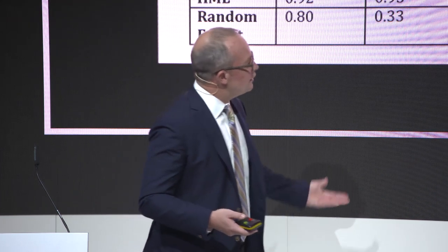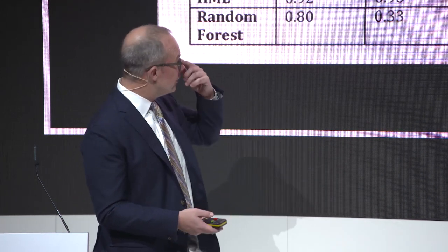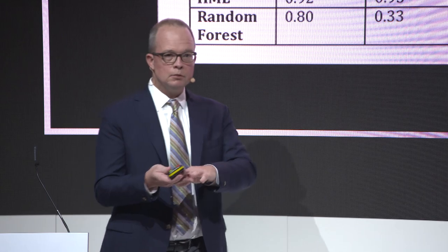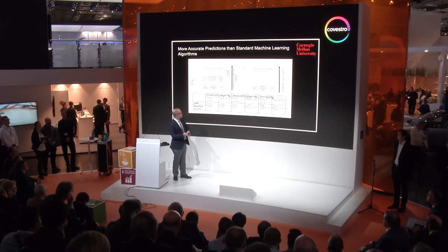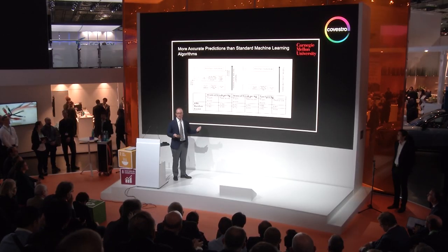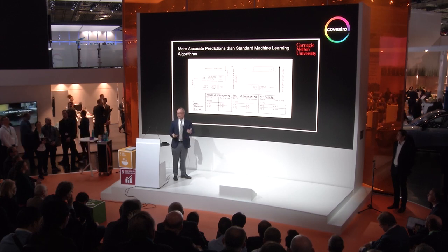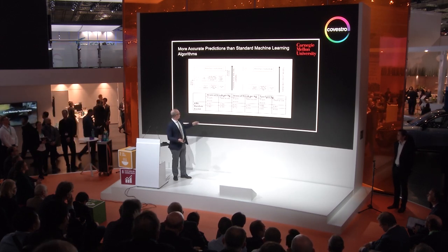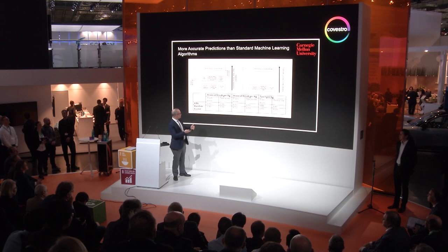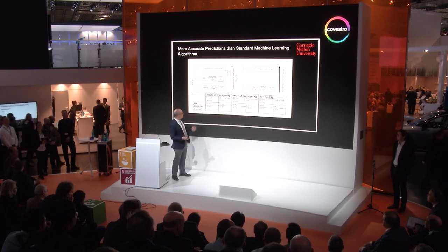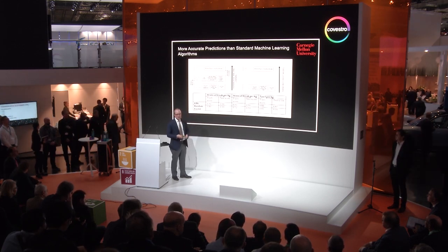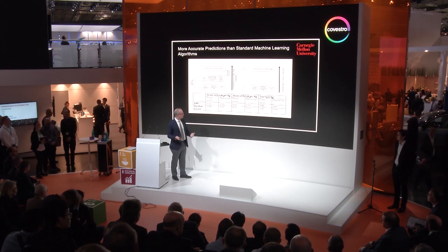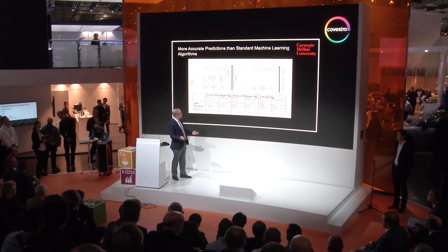So finally, in terms of the quantitative performance, in machine learning there are a couple of primary tasks that you're doing. The first is that you train your algorithm, and then you test the algorithm on data that it hasn't seen. And so what we've done is a head-to-head comparison of the hierarchical machine learning algorithm with a state-of-the-art black box model for machine learning that's used commercially.